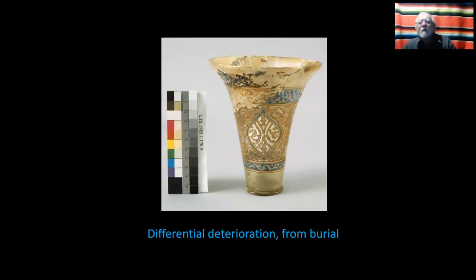We can get irregular preservation in glass. It's a very good example of an Islamic beaker that must have been buried at an angle, maybe in a drain or maybe in mud, and then partially exposed to an aggressive environment. The aggressive environments for glass tend to be alkaline. Anything with an alkaline pH is eventually going to do more damage than a neutral or acid burial. And so this piece, you know, very different preservation. The enamels are completely gone at the top, and even the glass is etched.